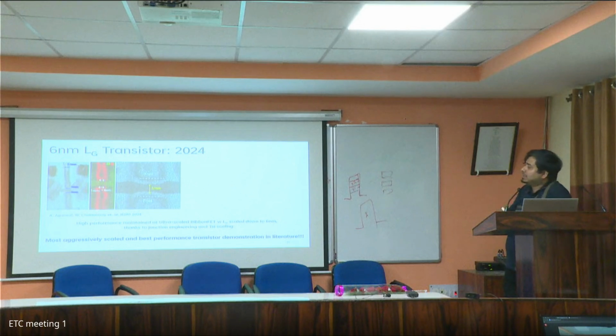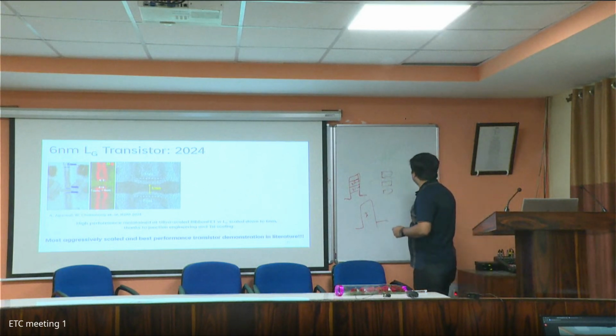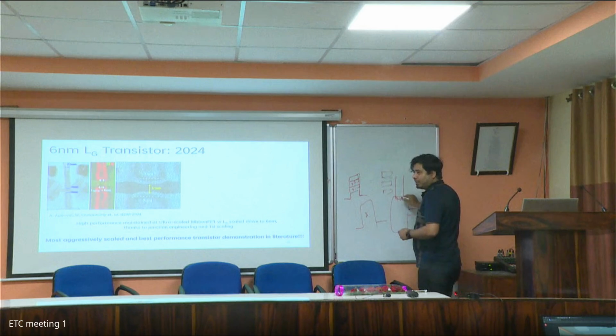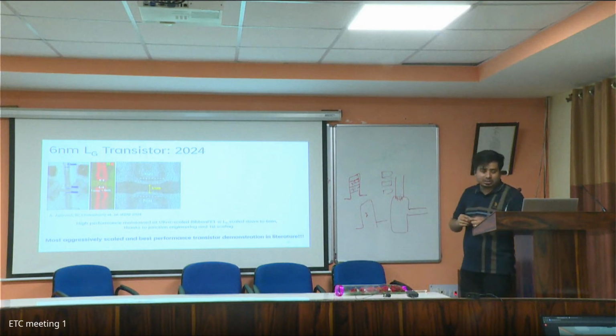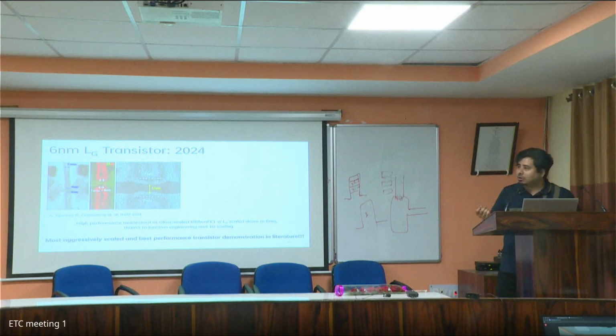The hardest part is the interface. If I have to just draw, say these are your nanosheets, these are your source drain epi, and this is where you're putting your contact. The biggest challenge is at this interface, because no matter how you grow it, there will be some oxides, some other contaminations, which will always hit your interface resistance. It will also cause challenges like pinning, because you can keep on changing the metals, expecting different work functions, but eventually it will pin to the same level.